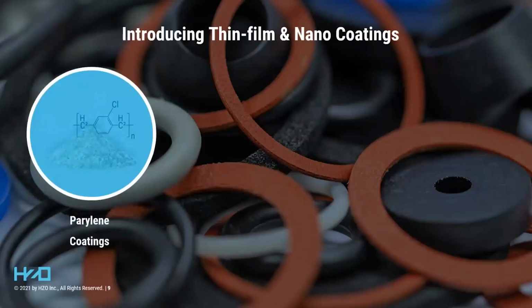I'm going to address the 3 major classes of thin films encountered outside of semiconductor processes, though, here. So parylene, as I mentioned before, it's deposited using a chemical vapor deposition process, or CVD. The coating is polymerized from a reactive monomer. It enters into the vacuum chamber from a thermal delivery system, which makes Parylene just a little bit different than some of these other coatings we're going to talk about. It's considered the gold standard, as I mentioned. First found widespread use in aerospace applications in the 60s, where weight and reliability were critical.